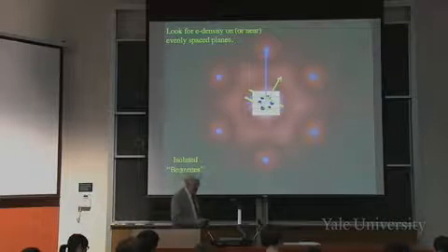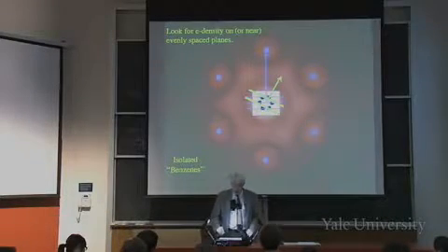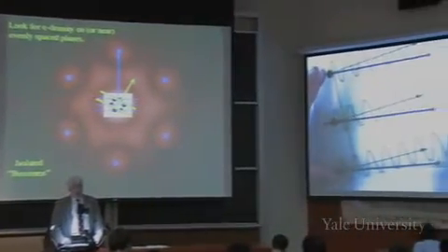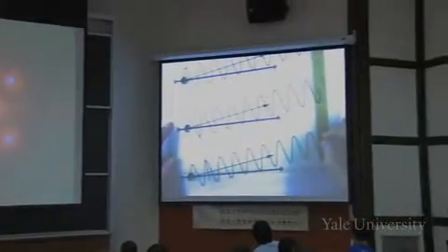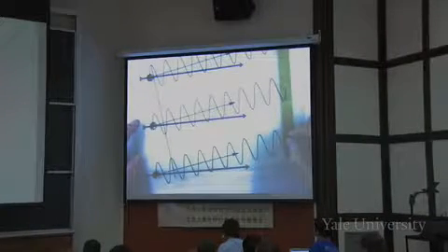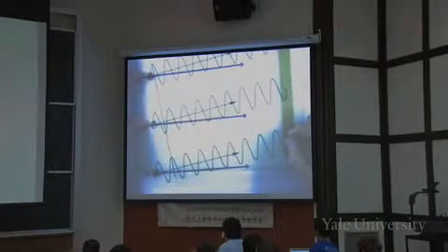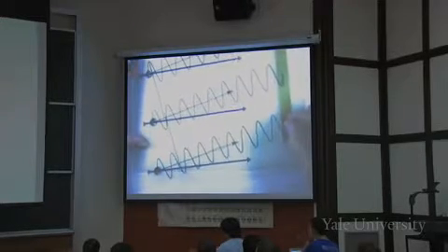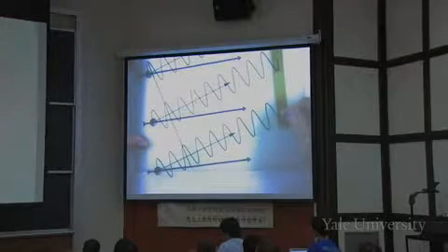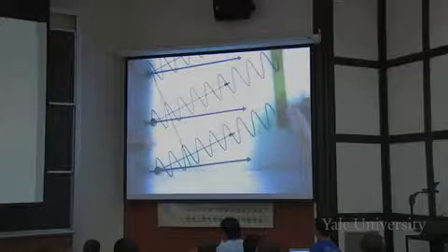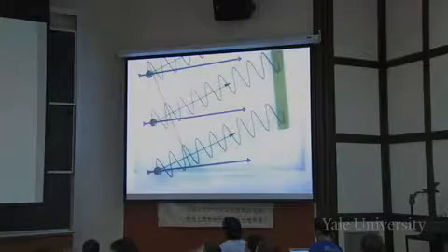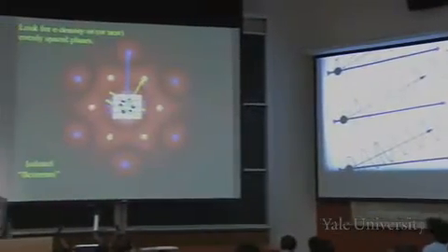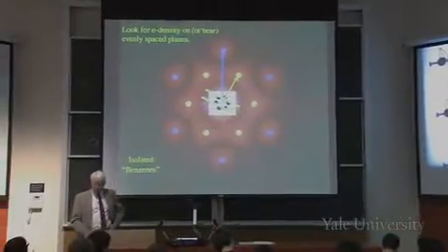And you can see immediately why that is if we look at this thing, that if you look at the top to the bottom where they're far apart, the lines are far apart, you get the first reflection there. But if the lines are closer together like these two, then you have to go to a higher angle in order to get that first one coming into phase, right? So that's that reciprocal relationship. Okay, so we get a set of 6 dots like that, and that's most of the pattern.